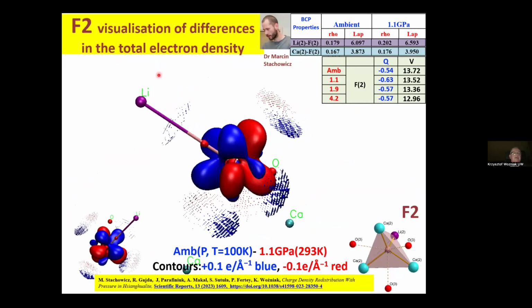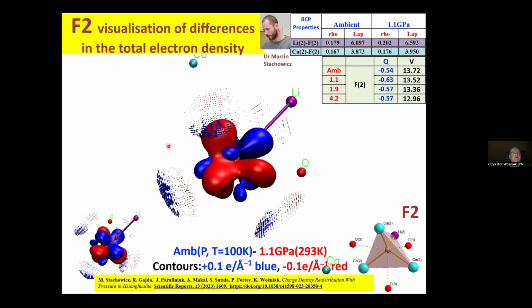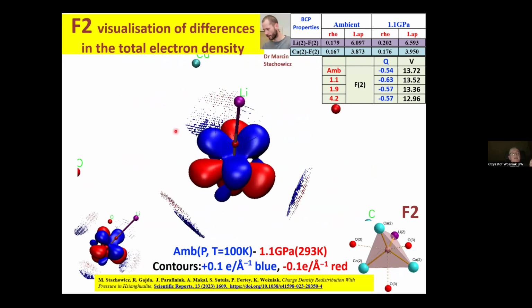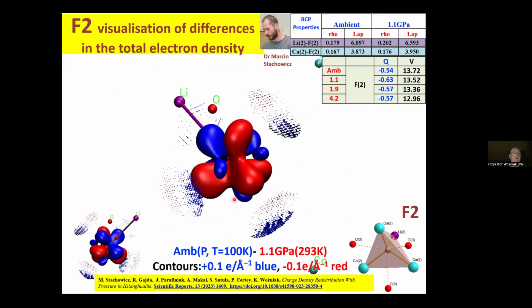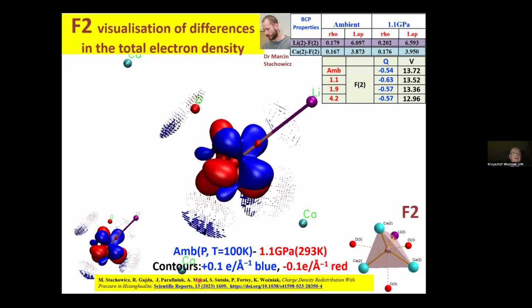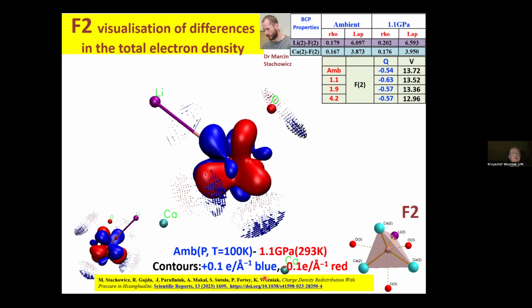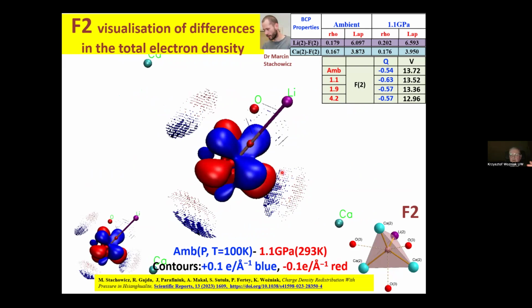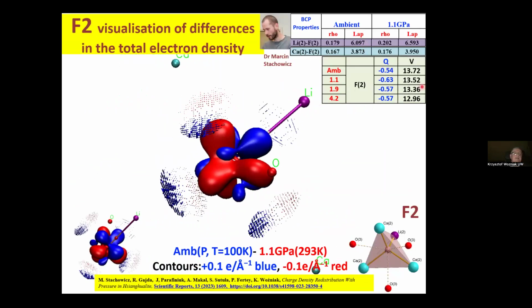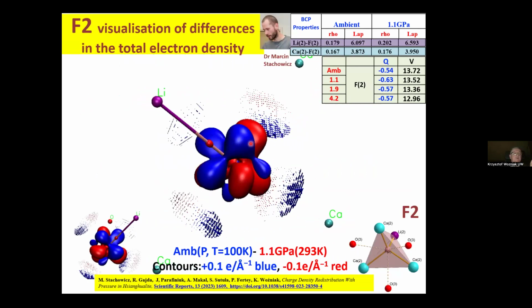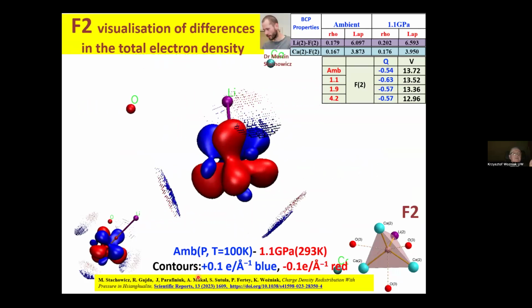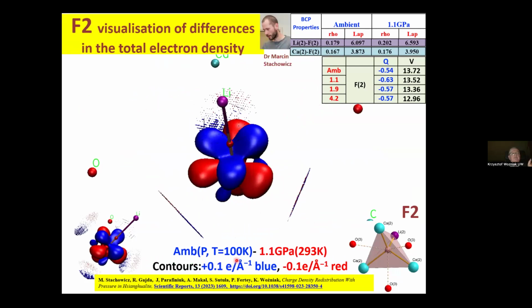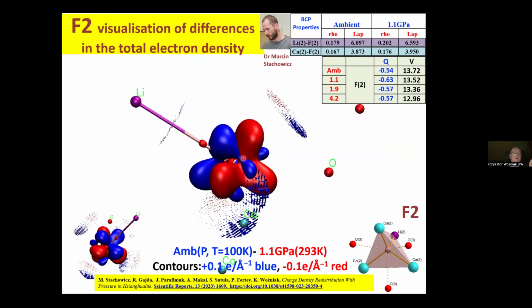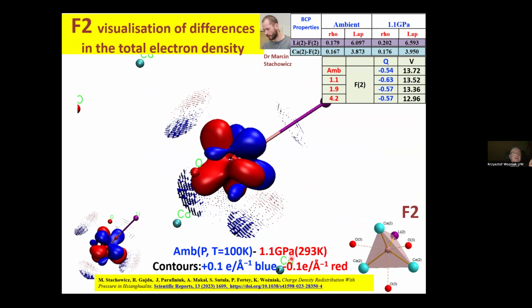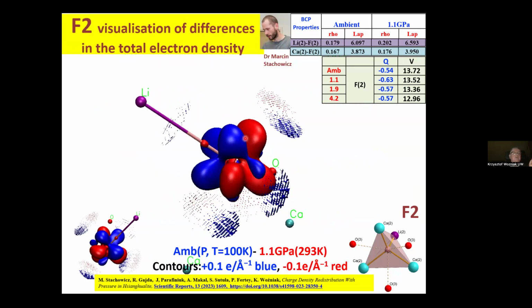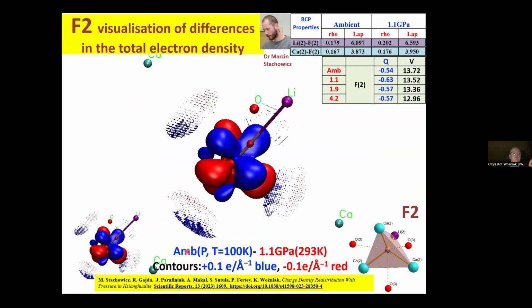But we can look inside the atomic basin. Here we see the differences in total atomic electron densities, and these differences are calculated. The contours are at 0.1 electron per cubic angstrom and minus 0.1 electron per cubic angstrom. How could we interpret them? In these blue fragments, there is 0.1 electron per cubic angstrom more at ambient pressure and 100 K than at 1.1 gigapascal and 293 K. And when we move to this higher pressure, in this red area, there is 0.1 electron per cubic angstrom more than at these blue conditions.